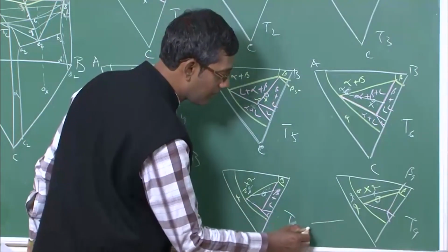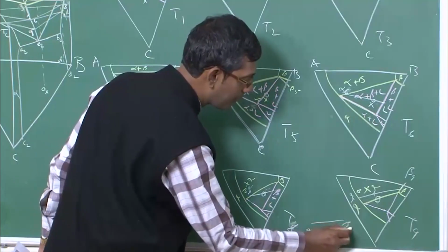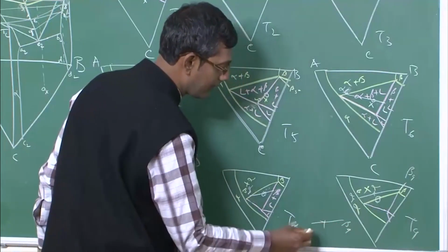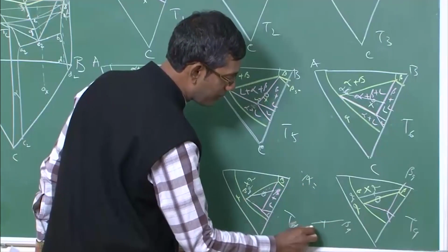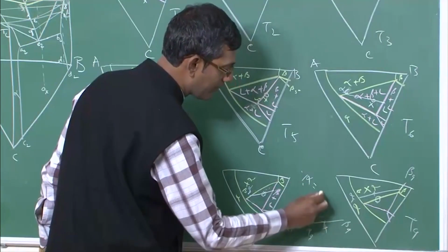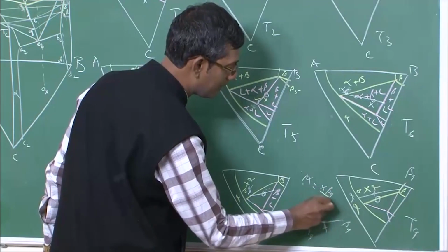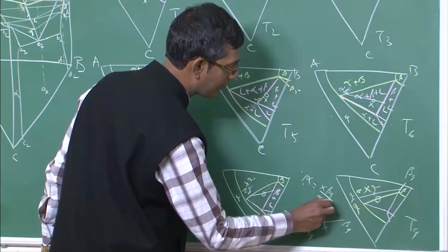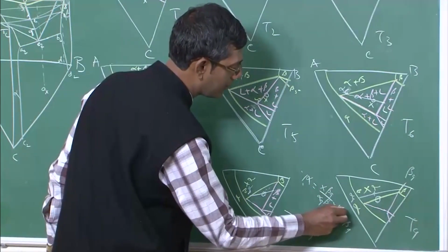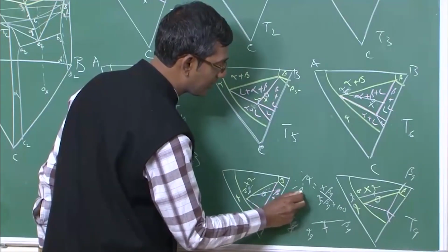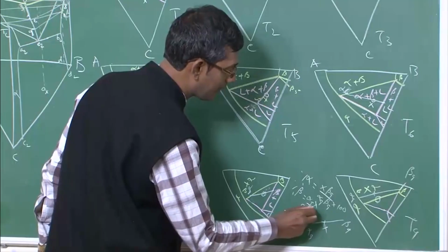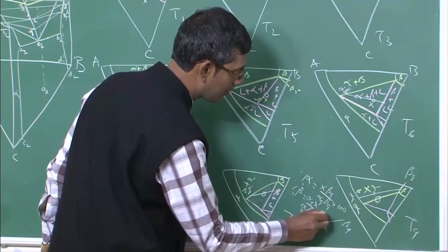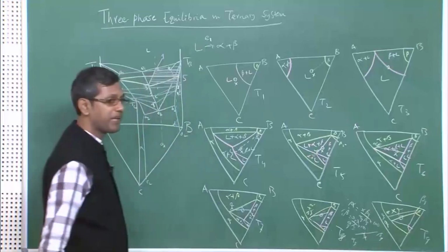So, I can draw alpha naught, beta naught and x sitting over there. So, percentage of alpha is nothing but, suppose this is x, x beta naught divided by alpha naught beta naught into 100. Percentage of beta is exactly the same, alpha naught x divided by alpha naught beta naught into 100. Because of space I am just writing there.